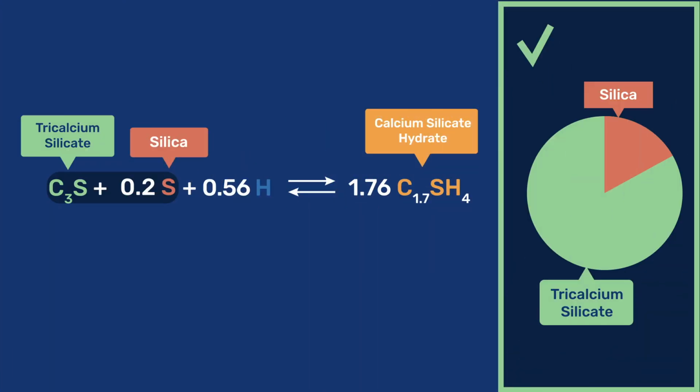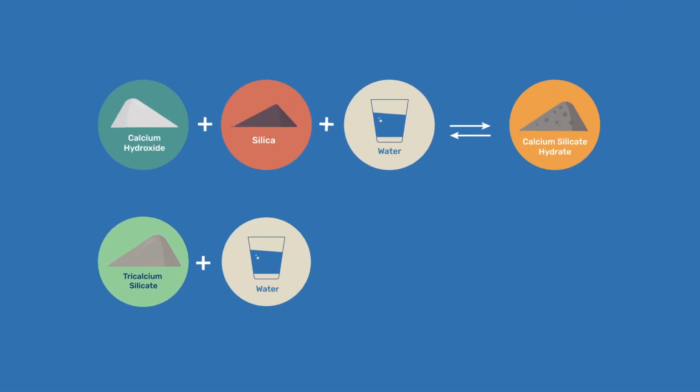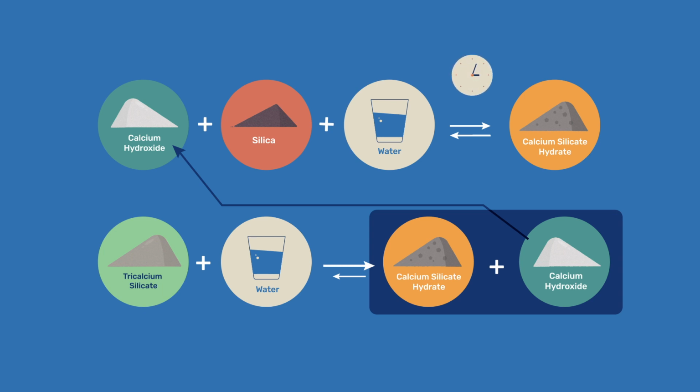So the above number should only be taken as indicative, even if it points to a much more important and fundamental issue, which is that in blended cements, the pozzolanic reaction is constrained by the amount of portlandite that cement hydration can produce and by inherent reaction kinetics of the pozzolan.